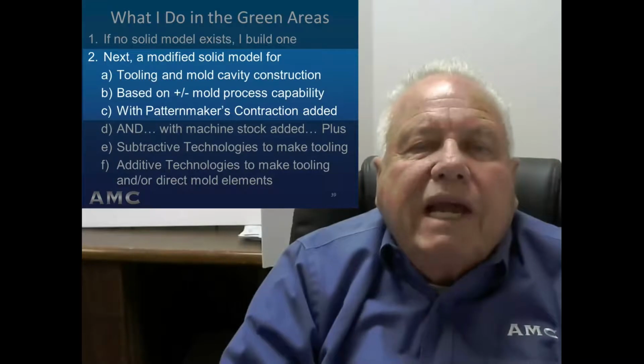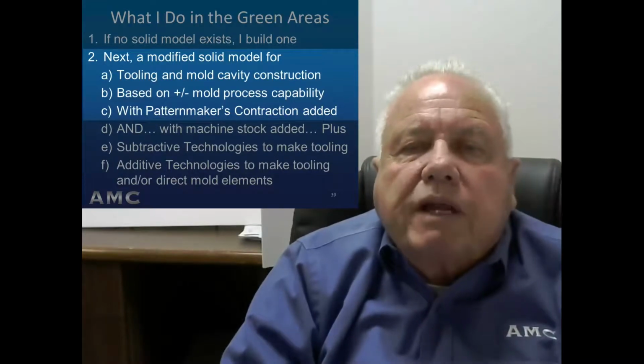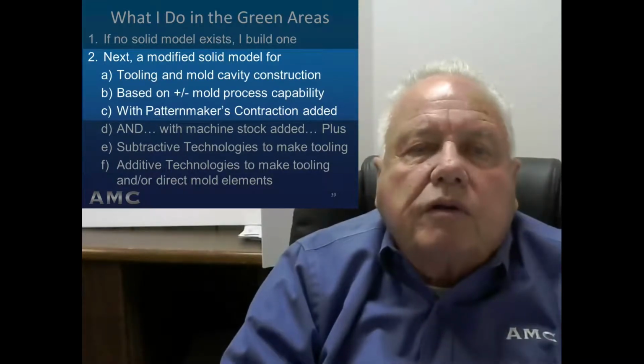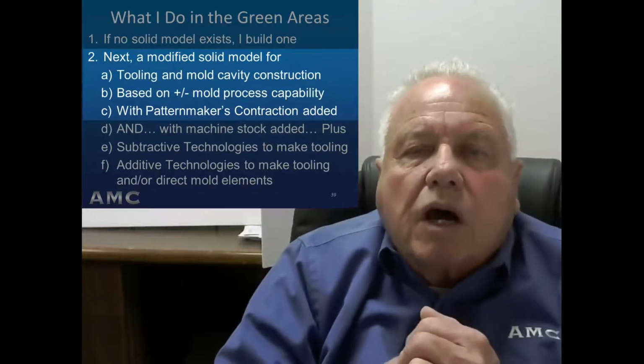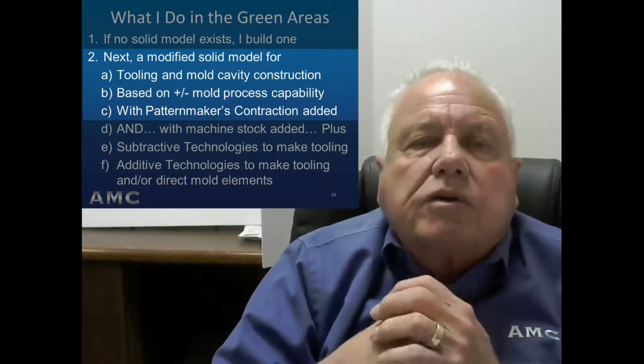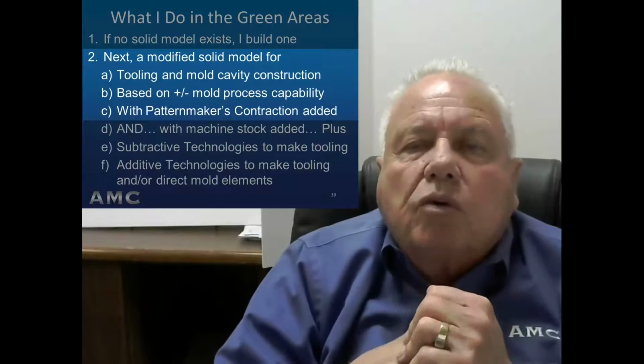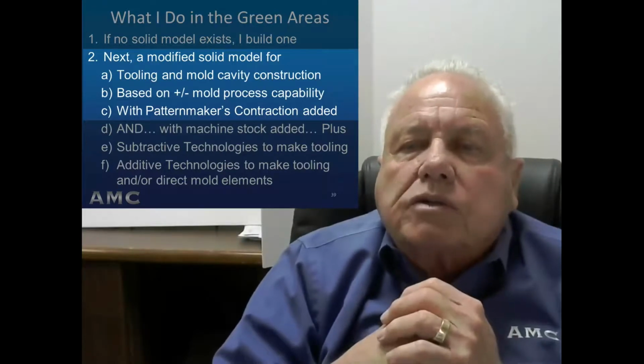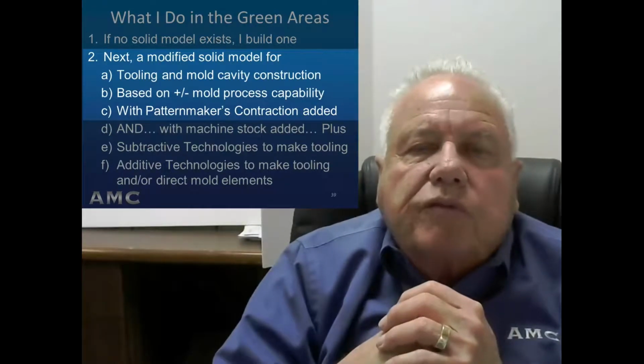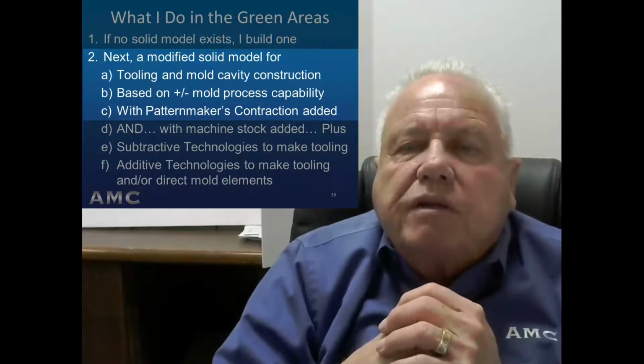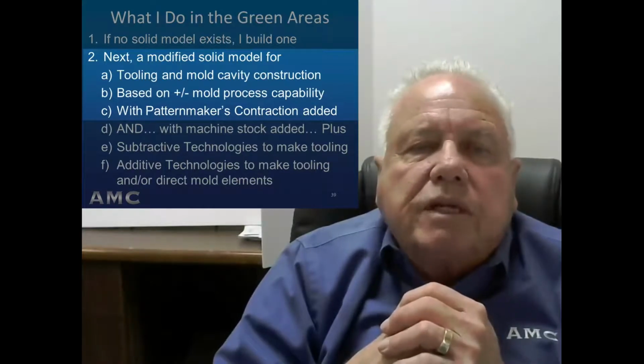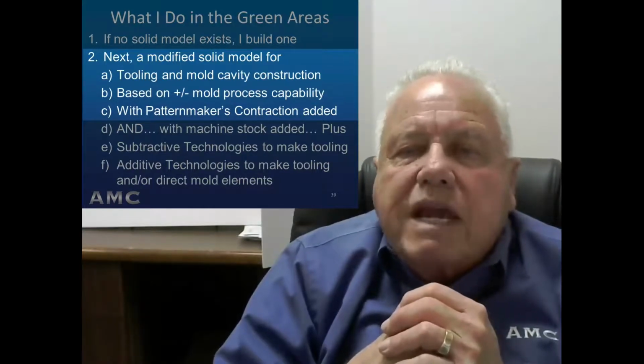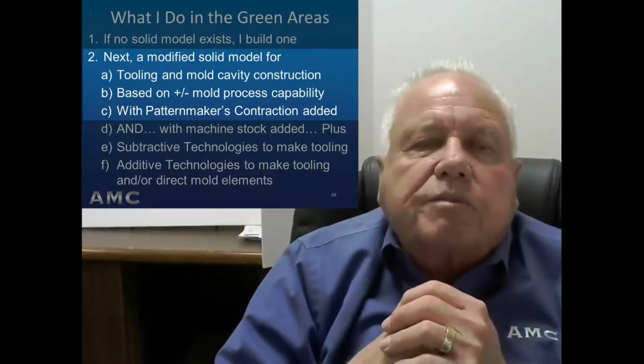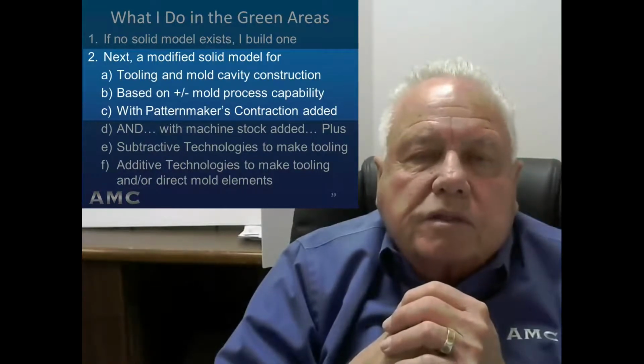This geometry is what defines the actual as-cast features of the casting as it is formed by the liquid metal. As a preface to estimating the pattern maker's contraction rate for all of the features in the second model, I convert all of the GD&T tolerances of position and profile to old school plus-minus coordinate tolerances. I do that because building tooling for the mold cavity has to be converted to plus-minus, just as the dimensional capability of the mold making processes is necessarily expressed in the old school plus-minus process.